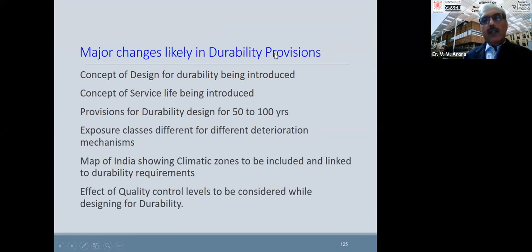So the major changes which are likely in the durability provisions: the performance-based design is coming up. The concept of design for durability is being introduced, that this is a performance-based design. The concept of service life is being introduced. Provision for durability design for 50 to 100 years. Exposure classes are different for different deterioration mechanisms. Today our exposure classes are not different. We say whether it is a carbonation mechanism or a chloride mechanism, we don't differentiate it. But Eurocode has different exposure classes where the critical deterioration is carbonation and where the critical deterioration is chloride attack. So we have different mechanisms, so we should have different exposure classes.